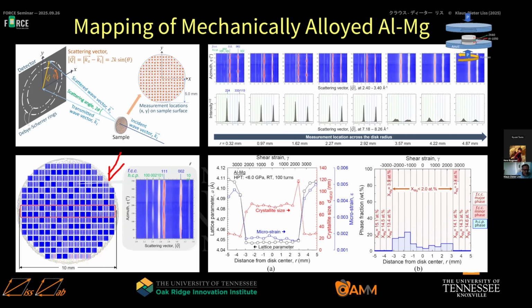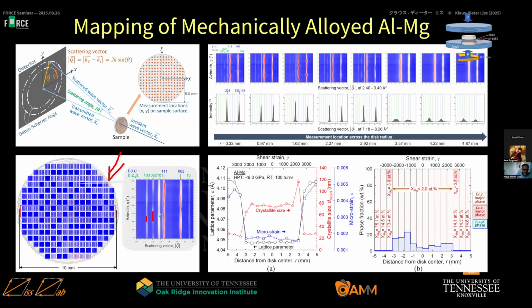So as a function of position, we get all these diffractograms here, at least where something is filled, and we see that there's magnesium phase, and there's aluminum phase. So aluminum 111 and 002. And eventually, as we can see here, there's magnesium. As a function of position here, the radius is given at the bottom. We see eventually the magnesium lines disappear. So we go into solid solution.